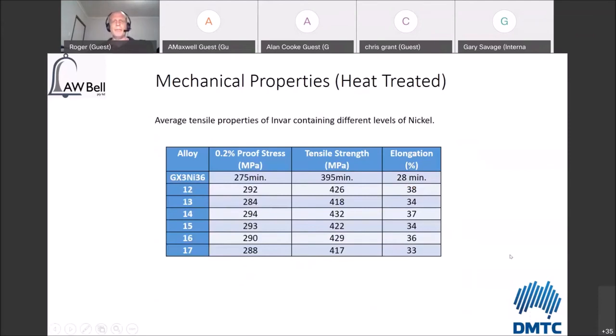Now, mechanical properties, this is the average tensile properties of the Invar containing the different levels of nickel. They're all basically the same. I wouldn't say there's any great variation here. Generally for Invar, you're going to see around about 280 to 300 megapascals proof strength, around 400 to 430 megapascals tensile strength, and around about 30 to 40% elongation.